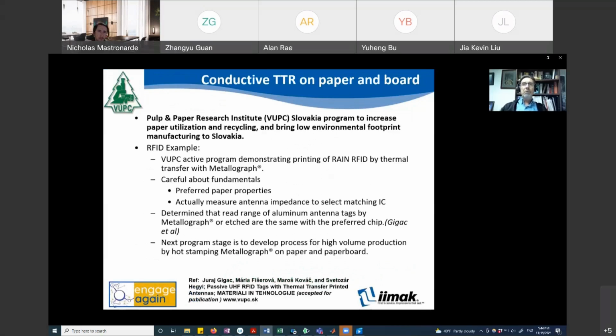Work at the Pulp and Paper Research Institute in Slovakia, called VUPC, is using metallograph to print RFID tags right onto paper in an effort to enhance the recyclability of paper packaging materials by eliminating the plastic inlays from the waste stream. In addition to printing directly on paper, VUPC has done some careful work to match chip and antenna impedance and found that the read range of a tag using a metallograph printed antenna was equivalent to that of the inlays using etched metal antennae.